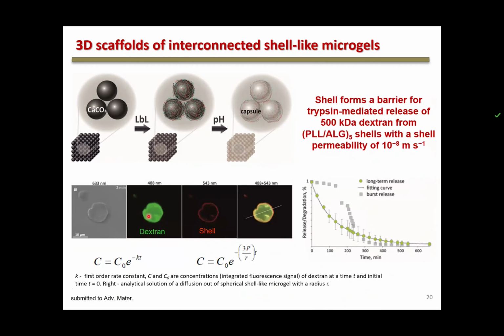And if you encapsulate inside, in this case it was again dextrane inside, and here we form the real capsule, so they have no matrix inside but a shell made out of multilayers, which is a well-defined shell. And by the assessment of the release kinetics of dextrane outside of the shell, using the analytical solution for 3-dimensional release, we have been able to extract permeability coefficient for such multilayers, and this helps to understand basically how these 3-dimensional scaffolds can serve as the scaffolds for tissue engineering, for instance.